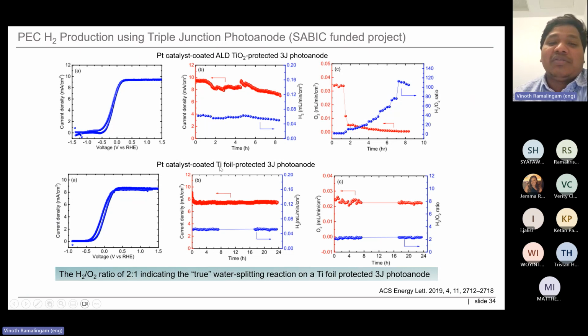So what we did finally, we put a Ti foil, a thick foil, a few micron thickness, and then coated Pt on top of it. In that case, we got a stable hydrogen, as well as when we started measuring oxygen, the oxygen was also stable, and it also maintains the stoichiometric ratio of 2:1, which indicates a true water splitting reaction.